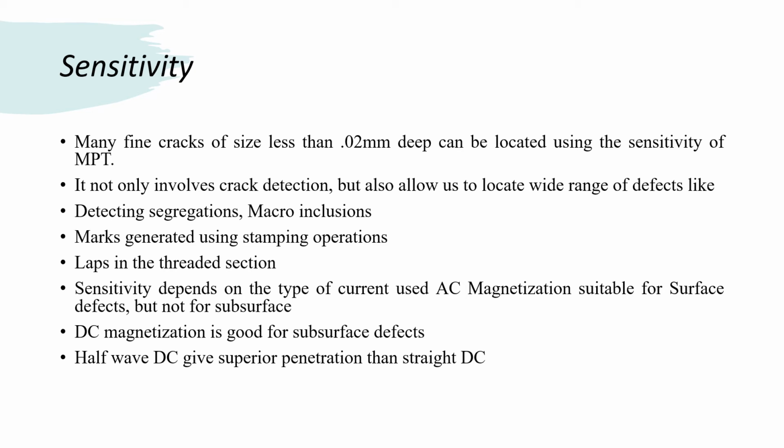If the defects are short, usually cracks, a comparatively low level of magnetic force will give sufficient buildup. However, to find minute cracks or subsurface flaws, the flux level should be high.